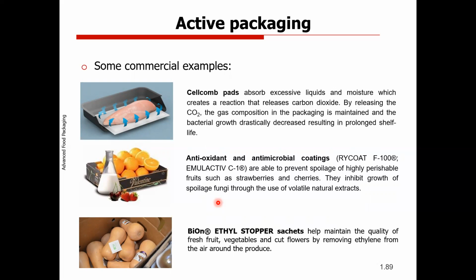Also, not in a primary packaging, but mostly in a transportation process. So you can call it a primary packaging and also a secondary package, but in this case, it's cardboard, where they apply a coating to this cardboard. It's RYCOAT and EMULACTIV. They are based in the active compounds that are released from the paperboard and then act as antimicrobial, inhibiting growth of spoilage fungi through the use of volatile natural extracts. So this is also a very interesting approach that some companies, in this case is one company that sells both, as using for fruits and vegetables.